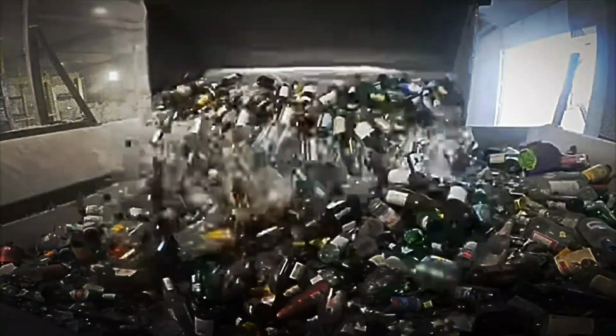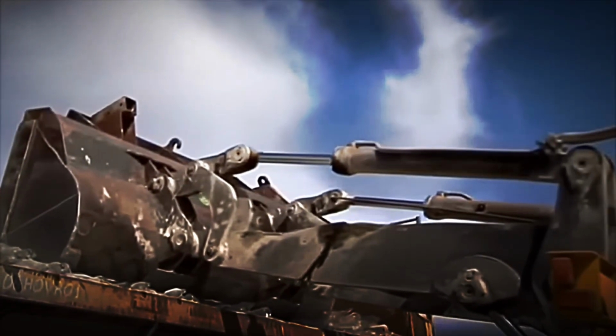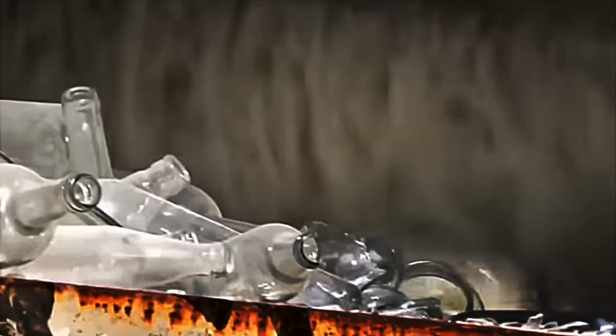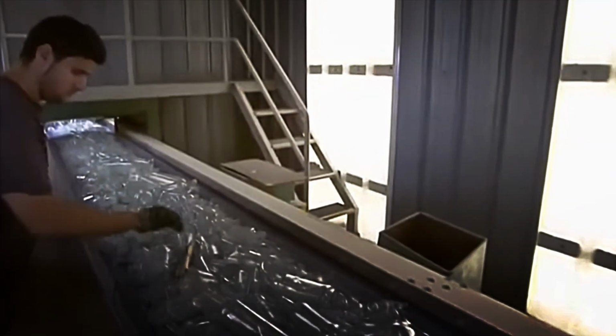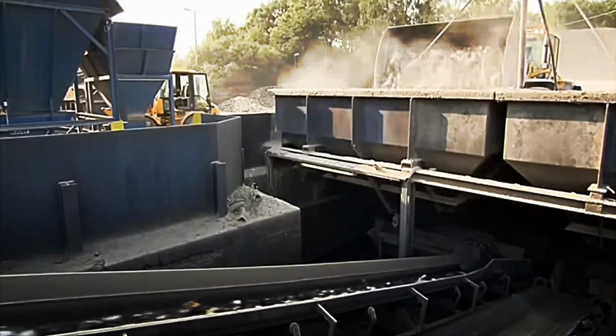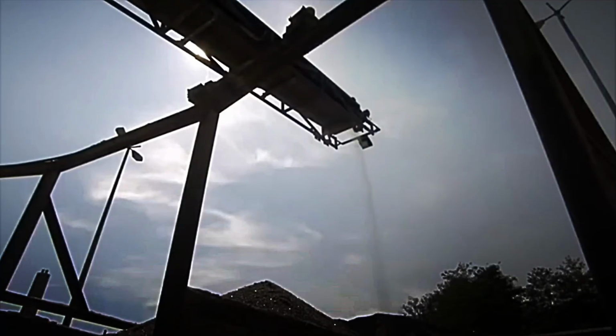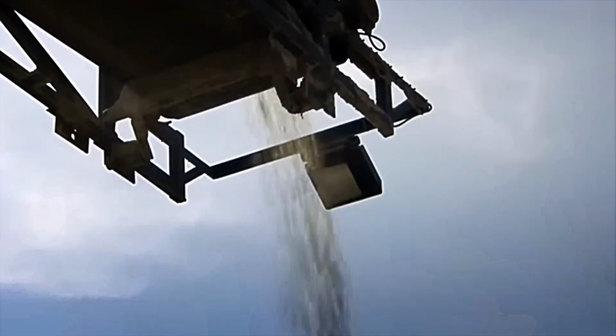This industrial equipment, fueled by natural gas, can reach temperatures close to 1,650 degrees Celsius, far hotter than volcanic lava. Its interior is lined with refractory materials that withstand constant heat without degrading, maintaining process efficiency and safety. Due to the extreme conditions, workers near the furnace wear fire-resistant suits with layers of aramid fiber, reflective aluminum, thermal gloves, and face shields, allowing them to endure the heat radiation and hot air. The furnace is charged using large-capacity crucibles capable of holding and heating the mixture in a controlled way.